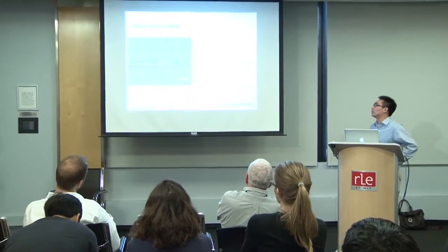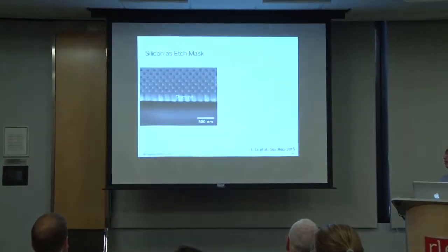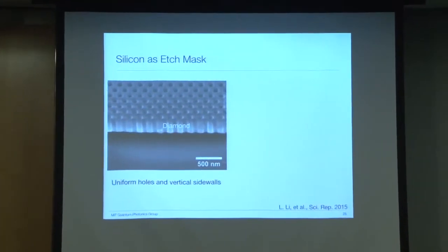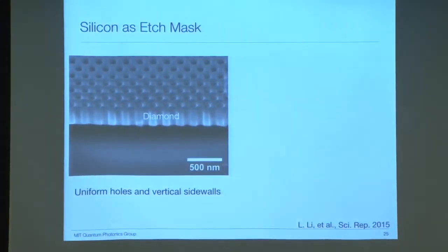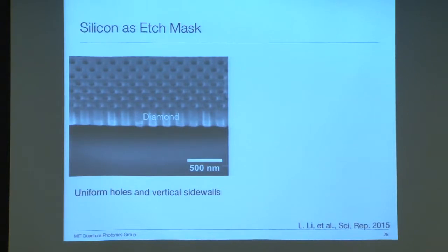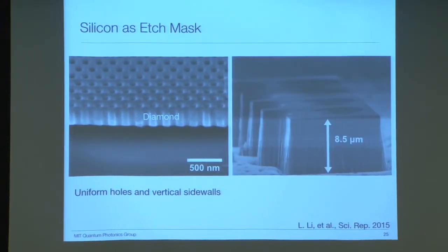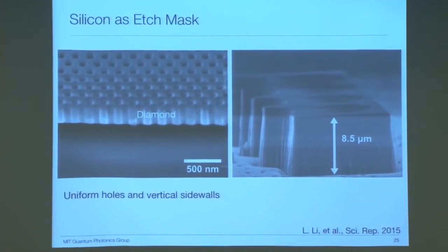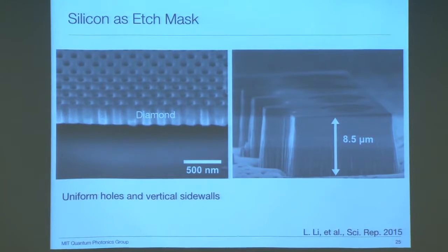Silicon is a good etch mask material for oxygen plasma etching of diamond. As you can see, the holes are uniform and the side walls are vertical. We also did a test by placing a silicon membrane on top of a bulk diamond, and we etched down until we saw degradation of the silicon mask. The etch selectivity is about 38 to 1. In this case, we used a 220 nanometer silicon mask to etch into 8.5 micron diamond.